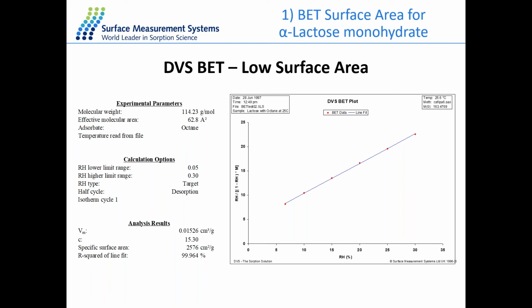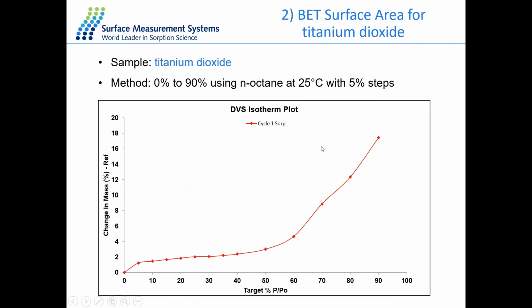And this value is quite consistent with the literature reported value for the pharmaceutical grade lactose sample. And as you can see, the R square shows a quite linear BET plot as well. So with the DVS, we can measure some very low surface area material with very good reproducibility. And we can also measure some high surface area material. Here is just an example with titanium dioxide.